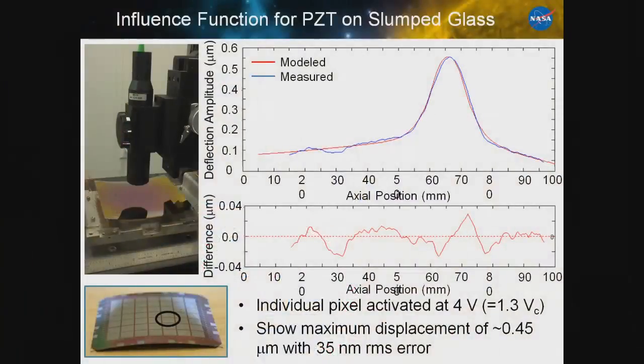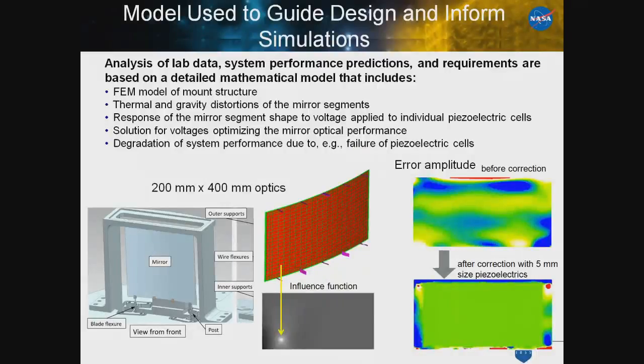And you can see here influence function data, where we've deliberately actuated one of the cells to produce a local deformation in the mirror surface. And you can see excellent agreement between the measured and modeled data. What this suggests to us is that we have deterministic control over the surface.